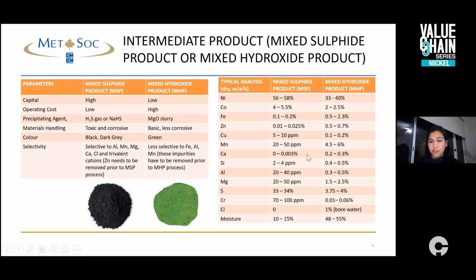Calcium is also very low with mixed sulfide, and silicon. Silicon is one of the controlled impurities as well. With mixed sulfide, it's down to ppm levels compared to around 0.5% for mixed hydroxide. Another thing to note is the moisture content of the intermediate product. With mixed sulfide, the PSD is much coarser and it's very easy to filter. That's why a moisture of around 10 to 15% is typical, compared to mixed hydroxide, which tends to absorb more water. As you can see, the moisture could get as high as around 48 to 55%.